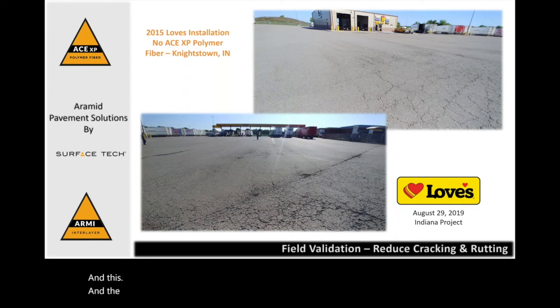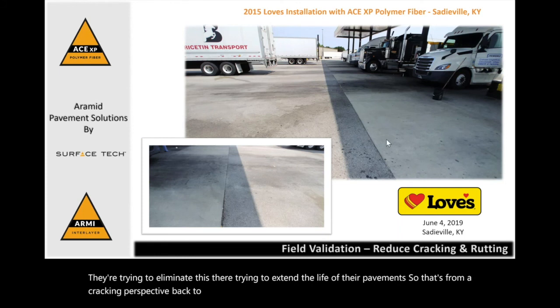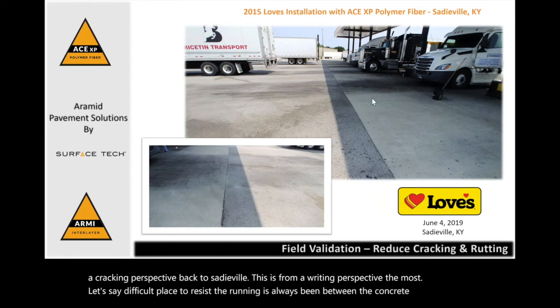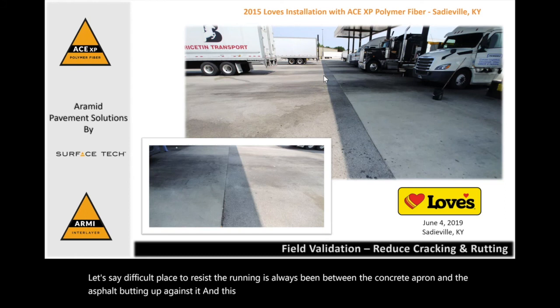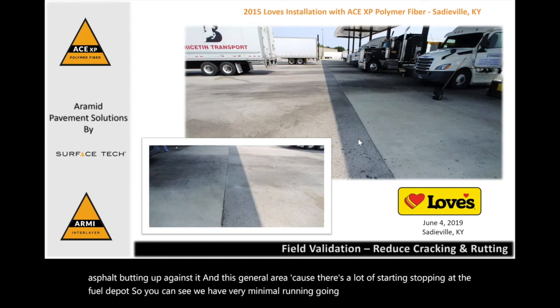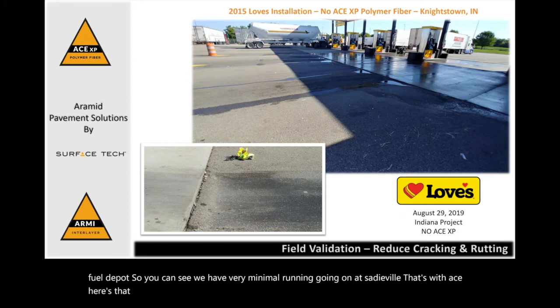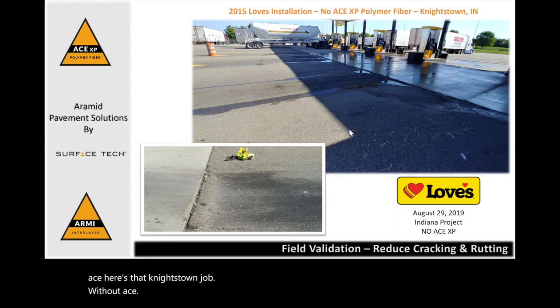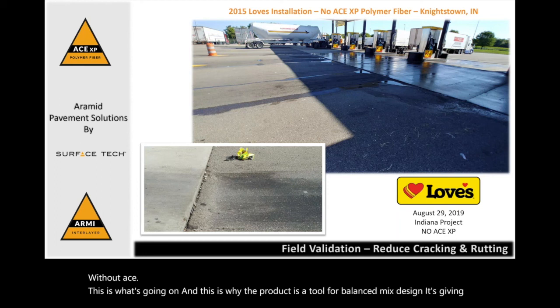And that's a reason why Loves has made ACE XP Polymer Fiber a standard on every new store that goes in. They're trying to eliminate this. They're trying to extend the life of their pavements. So that's from a cracking perspective. Back to Sadieville, this is from a rutting perspective. The most difficult place to resist the rutting has always been between the concrete apron and the asphalt butting up against it, because there's a lot of start and stopping at the fuel depot. You can see we have very minimal rutting going on at Sadieville. That's with ACE. Here's that Knightstown job without ACE. This is what's going on, and this is why the product is a tool for balanced mix design. It's giving Loves performance both in cracking and rutting.